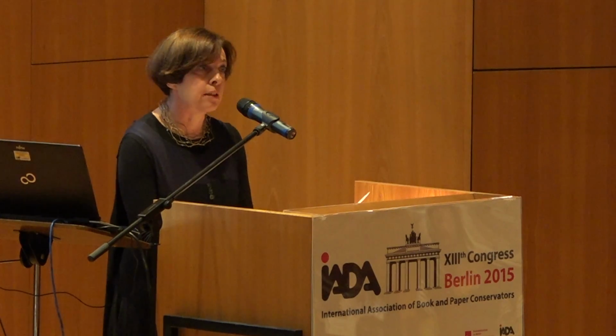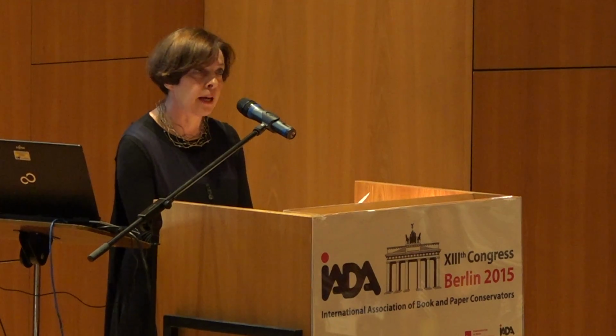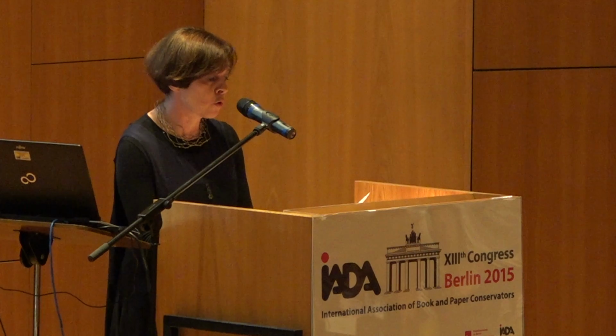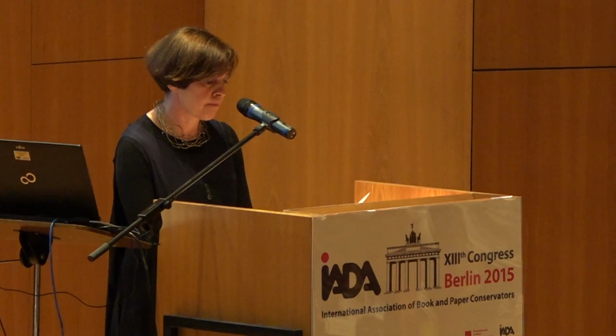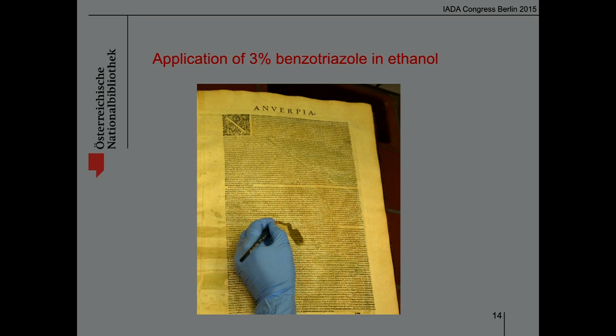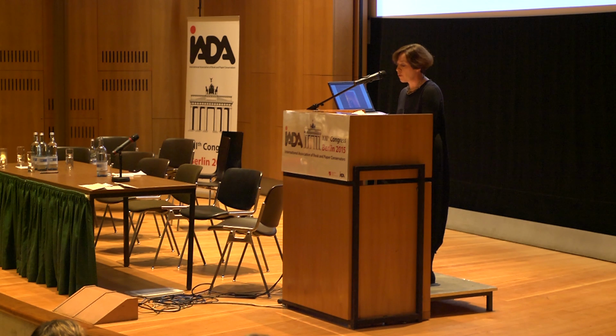A 3% solution of BTA in ethanol was applied with synthetic brushes to the verso of areas with discolored verdigris. The use of ethanol prevented deformation of the paper and mechanical stress to the brittle paper. Initial tests showed that a one-time application seems sufficient. The solution was applied from the verso with the aim of complexing copper ions and thus protecting the paper support. As BTA is harmful to health, the treatment was performed under a fume hood with protective garments.